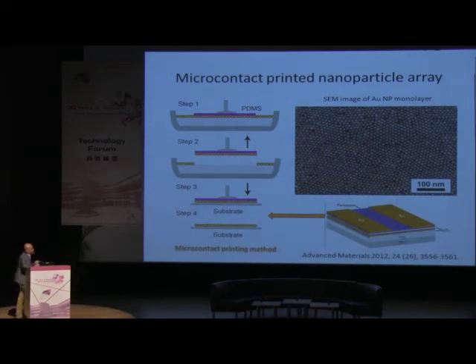Now, as a first part, we start with a contact printing method by using a metal nanoparticle, which is gold here, and using a simple PDMS stamp to transfer from one substrate to another substrate. And since they have a charge, they don't form multilayers, and they just form a beautiful monolayer. So we embed this layer between two aluminum oxide insulators. So when the charges are getting from the pentacene, the semiconductor, to the gold nanoparticles, these two aluminum oxide layers confine the charges in a particular monolayer. So the charges stay a much longer time than the previous devices.